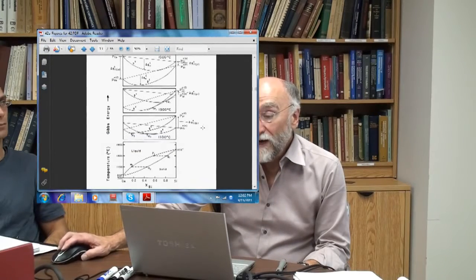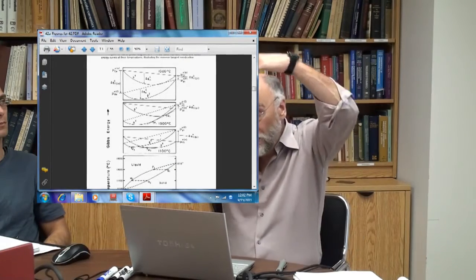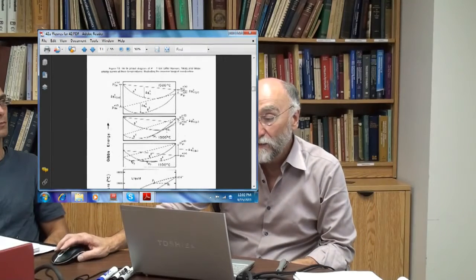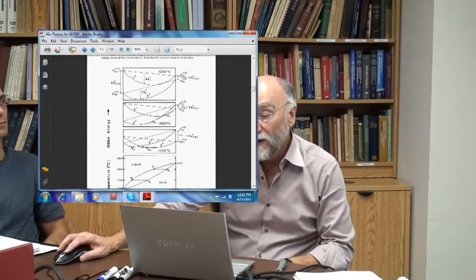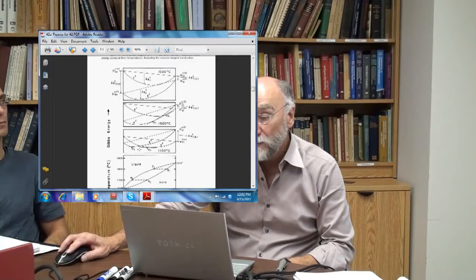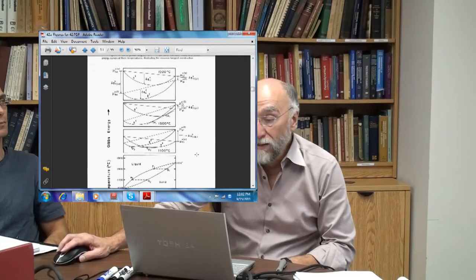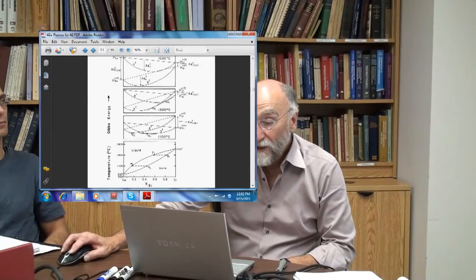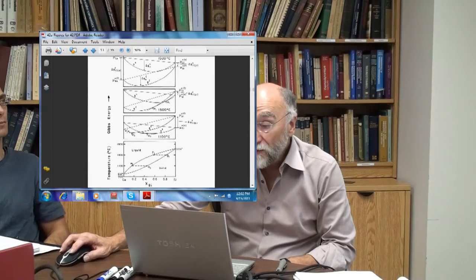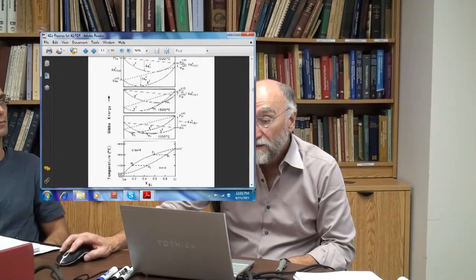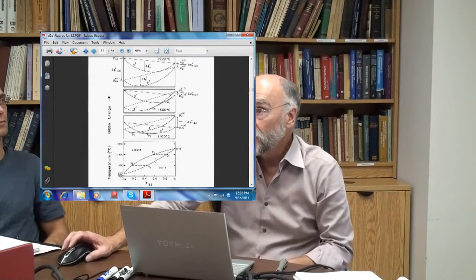Clearly then, as we move down to a lower temperature, the solid curve continues to go down through the liquid curve, and the common tangent line now at 1100 degrees has moved over here. And eventually, when you get to 938, the two curves touch at only one point, and below 938 the solid curve is always lower than the liquid curve.